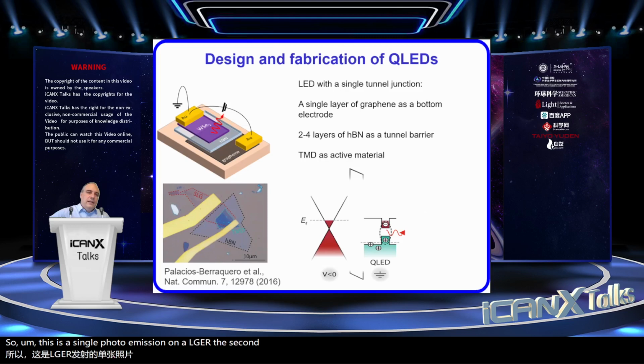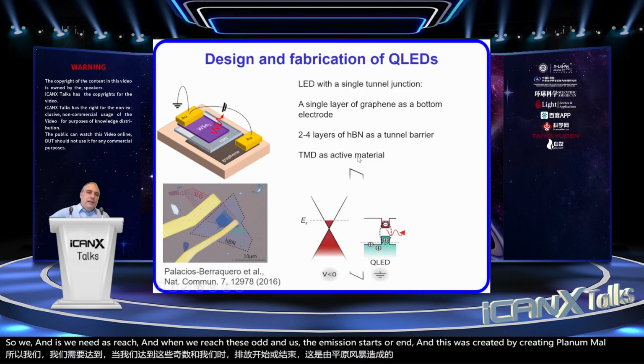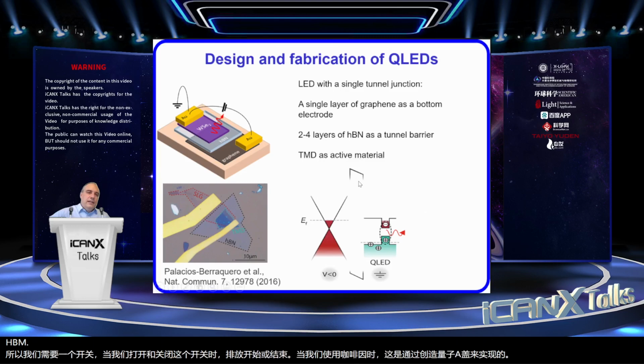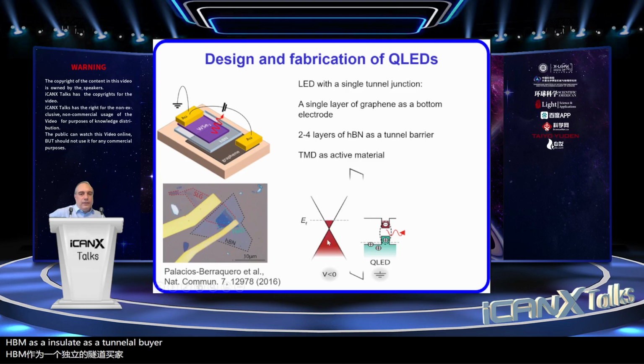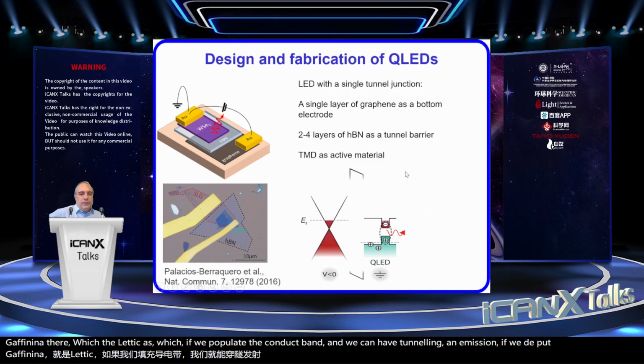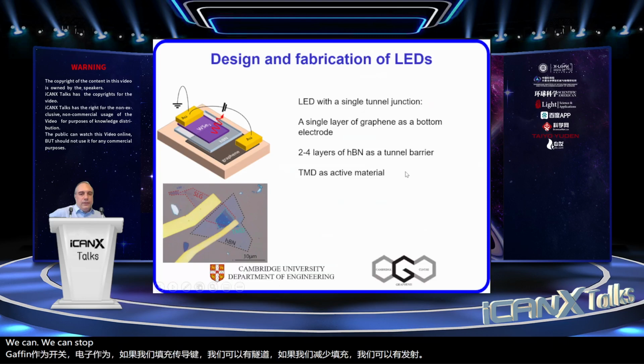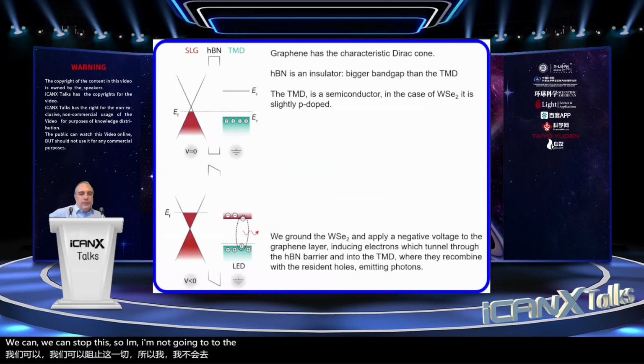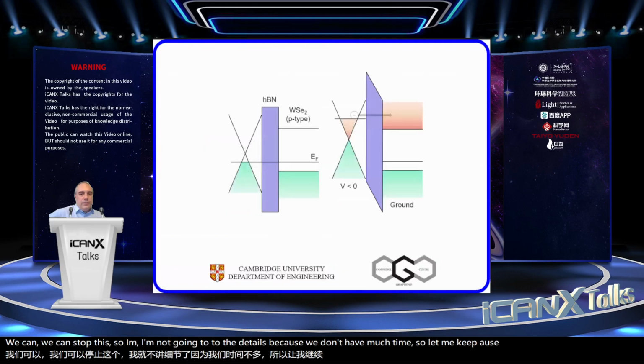The second point is we need to get them emitted on demand. So we need a switch, and when we switch this on and off, the emission starts or ends. And this was created by creating quantum LEDs when we use graphene, hBN as an insulator, as a tunnel barrier, and then the TMD. And by basically using graphene as the electrical switch, if we populate the conduction band, then we can have tunneling and emission. If we depopulate, we can stop this. So I'm not going to go into the details because we don't have much time. So let me skip a few slides and let me skip forward.